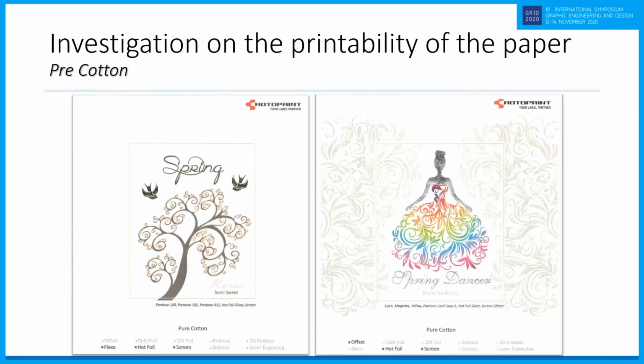The last part of our investigation was focused on the printability of the papers, connected with the results from the fiber content of the papers and their properties. Pure cotton is suitable for full cover offset printing, although the color density provided by the technology itself is not maximum. It also has an exceptional effect on the reproduction of elements and strokes with screen printing.